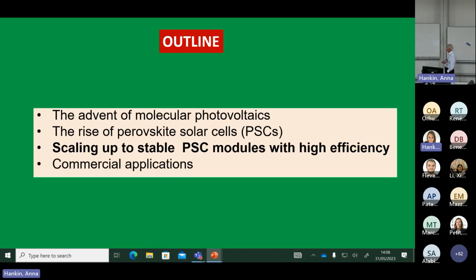And so now the hunt for higher efficiency, I think, is pretty much over, because people say, well, let's first stabilize what we have and see whether we can apply those highly efficient materials. We also need to scale up the module size. Most of these efficiency values are measured with tiny little devices, less than 0.1 square centimeter. If you go to 1 square centimeter, you already get a beating. The efficiency will go down, maybe from 25 or 26% to 24%.